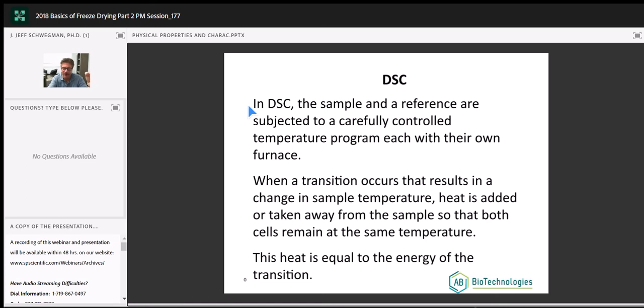Take the sample pan and the reference at zero or room temperature, cool them down. In the DSC, we can go down to negative 90. So we cool down to negative 90, hold it for a few minutes, and then warm it up to room temperature and look at the transitions. Now, the difference between differential scanning calorimetry and differential temperature analysis. Differential temperature analysis, we're simply measuring the change in temperature between the reference cell and the sample cell. In DSC, we're measuring the difference in heat flow.